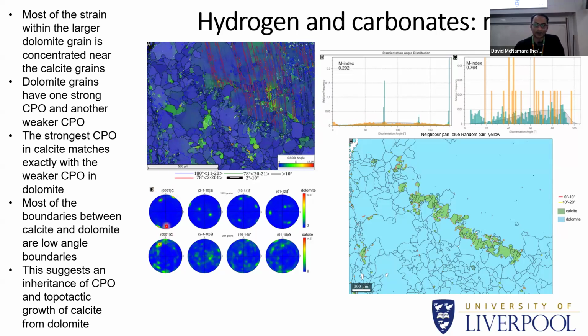And we see that there's a common orientation here. We plotted interface misorientations between calcite and dolomite. That's this map here. The light blue is dolomite and the green is calcite. And we see a lot of these red lines. These red lines are boundaries between 0 and 10 degrees, so very low angle boundaries. And we see that a lot of the boundaries between calcite and dolomite are low angle boundaries.